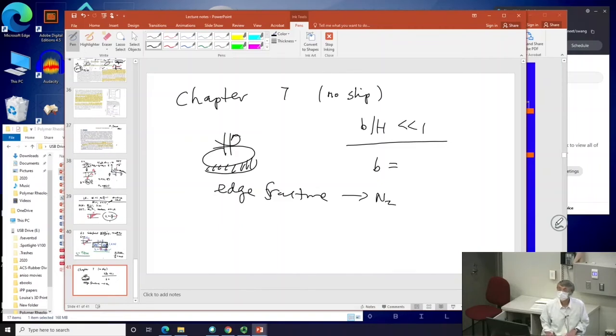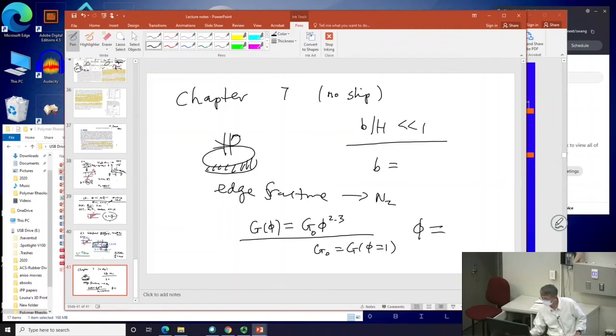Which means it's impossible for you to learn about rheology in the shear mode. That would be very, very, very unfortunate. So the way we do it, we do solutions. When you have a solution, it turns out you can make your solution much softer. Your modulus can be softer than that of the pure melt by a factor given here. So when you choose your solution to be only 10%, you bring down the stress level, which is dictated by the modulus, by a factor of over 100.